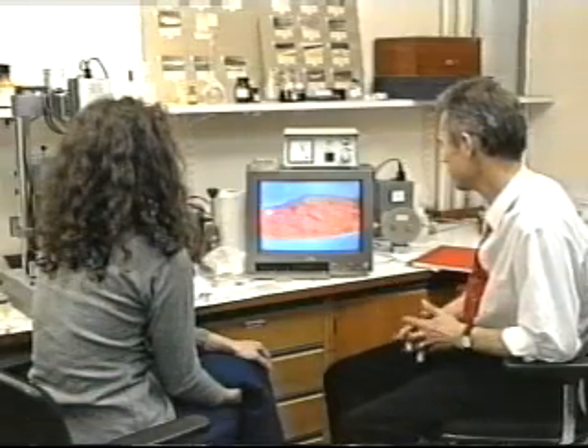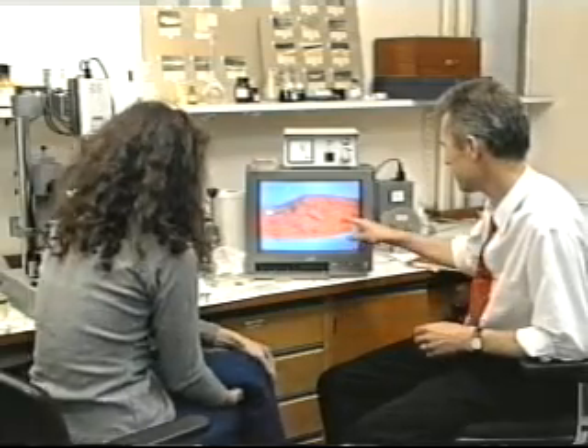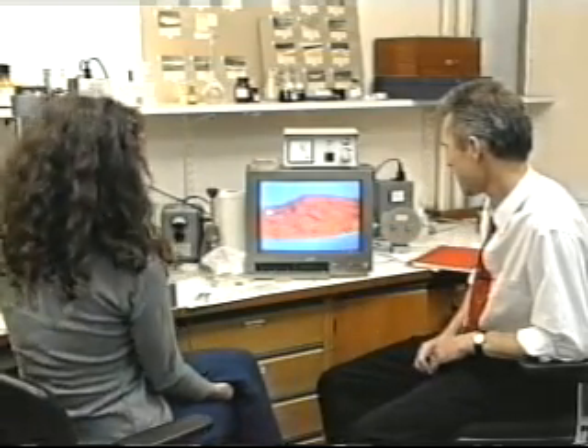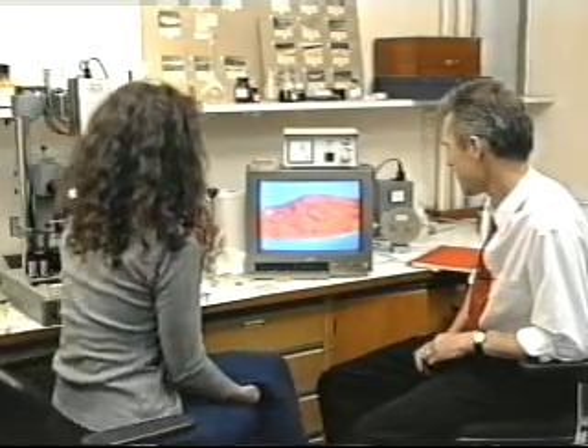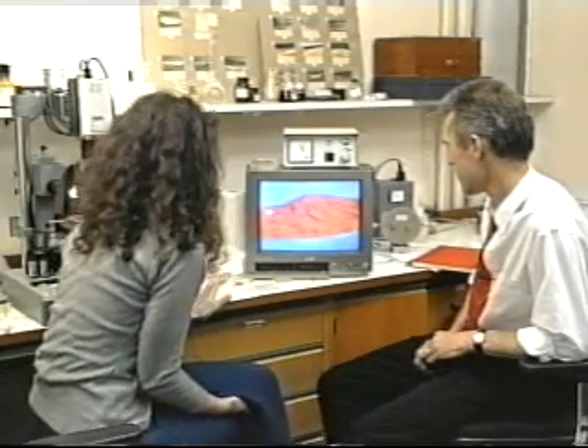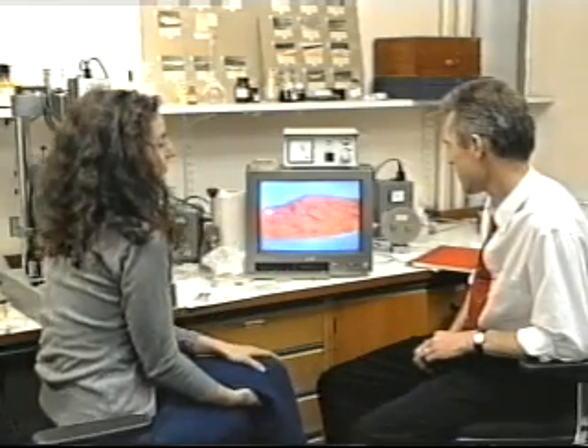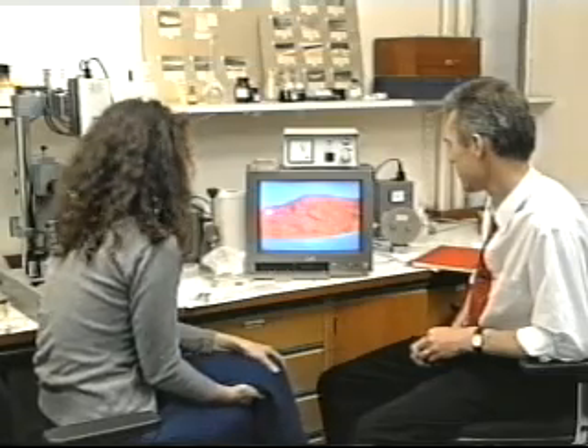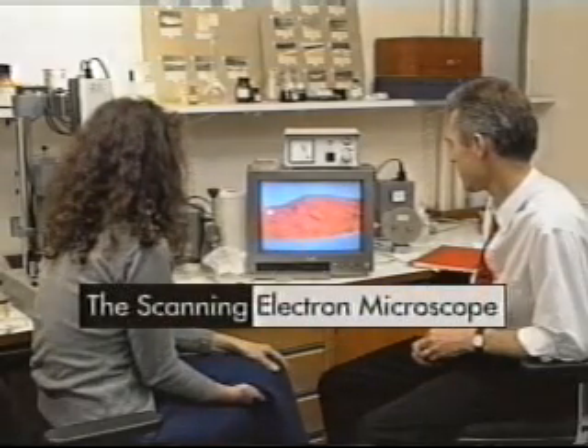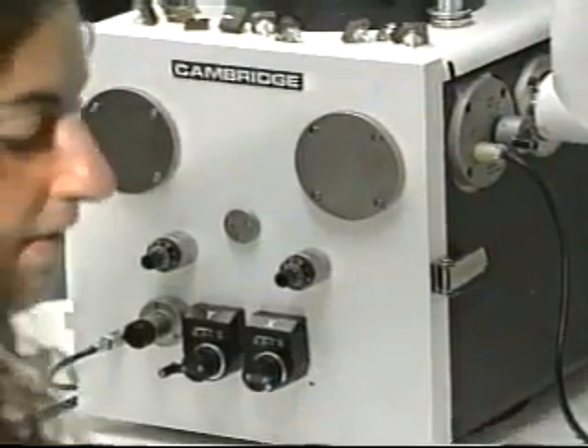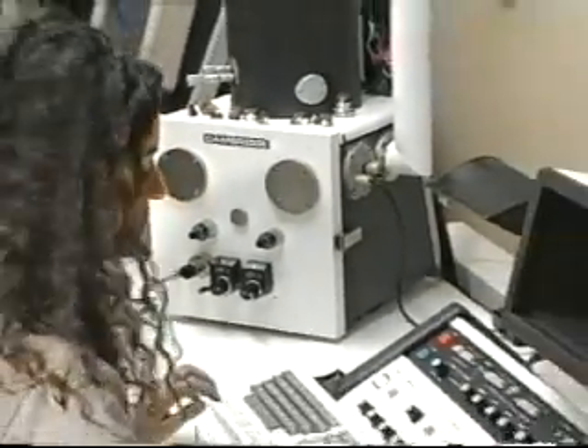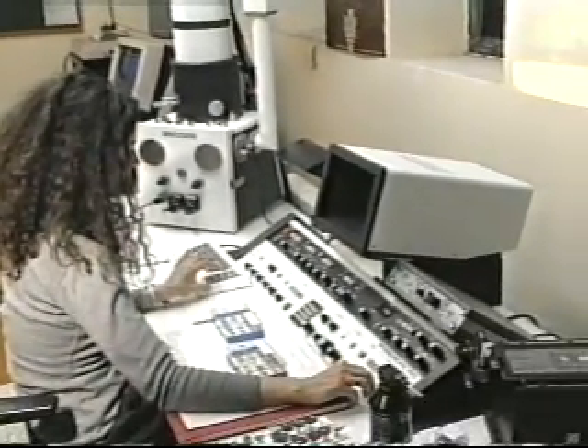So how are you going to discover what this pigment is? What I'm going to do is to take this cross-section, coat it with carbon, and perform an X-ray analysis on it using the large instrument next door. We were to discover how the machine next door, the scanning electron microscope, was able to sort out this mixture of two pigments. In the Rembrandt sample, the machine had found a reddish-brown iron oxide and the more crimson-coloured red lake.